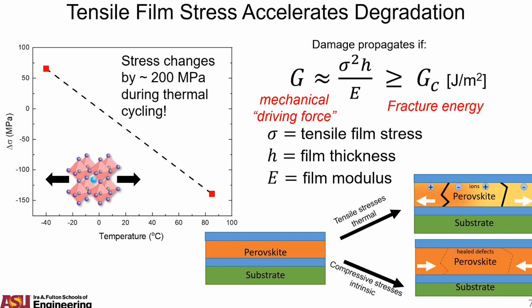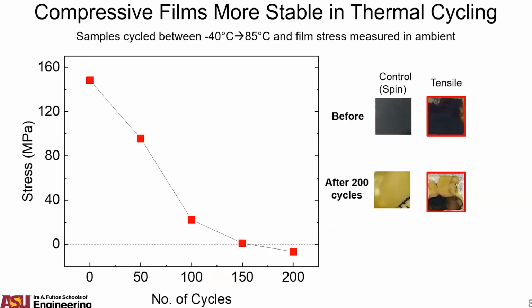And so thinking back to that formula, we're going to have degradation scaling with the square of this tensile film stress, and so we want to minimize that, and we've actually been able to engineer devices that have compressive stresses. And so what's being shown here are devices that were cycled between -40 C and 85 Celsius. And basically, the red indicates a film that initially had tension, and after 200 thermal cycles, it turned yellow, and that means it's no longer a photovoltaic device.